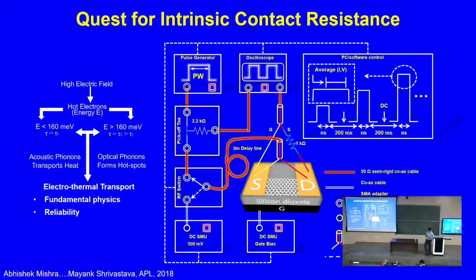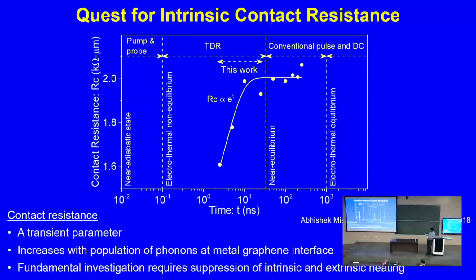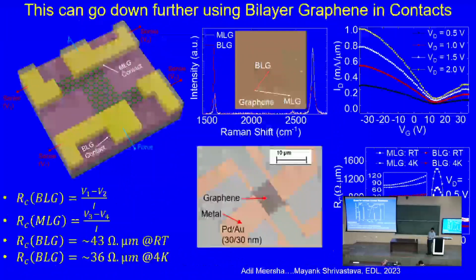Now we wanted to investigate whether this is the fundamental limit or there is something more. So we thought that possibly there is also a phonon limit in these contact resistances. So we built this setup which would extract the IV characteristic at nanosecond timescales, sub 5 nanosecond timescales, a complete RF setup. And what you see here is, as you scale the time scales from microseconds to a few nanoseconds, you see a significant further drop in the contact resistance.